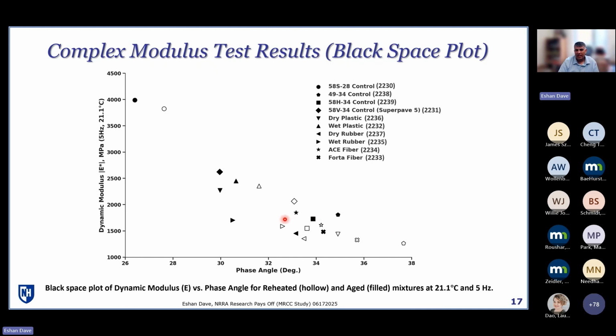The main point I want to make here is that aging is important, because each of these black or solid dots has a companion hollow dot. So this is for one of the mixtures, this is for another set of mixtures. And what we are seeing is, as we age these mixtures, two things happen. They stiffen up. As we go from hollow to solid, it's representing short-term or unaged condition, just a reheated condition, to aged condition. So they get stiffer, which makes sense.